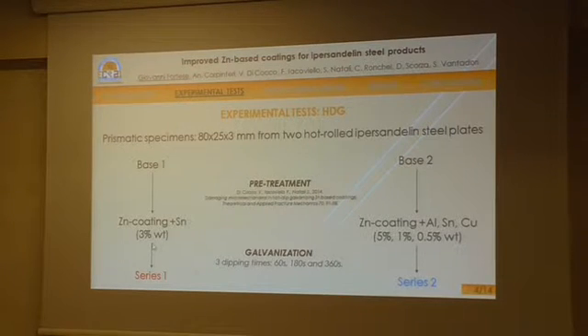And a bath consisting in a traditional zinc-based coating with additions of aluminium, tin, and copper in the measure of 5%, 1%, and 0.5% in weight, respectively. The corresponding series of specimens are named series 2 in the following. For each of the above series, 3 different dipping times equal to 60, 180, and 360 seconds were considered.